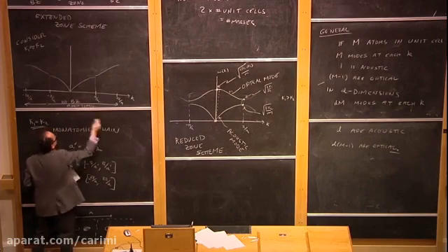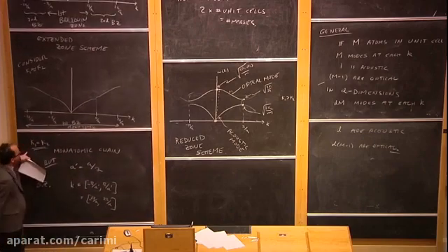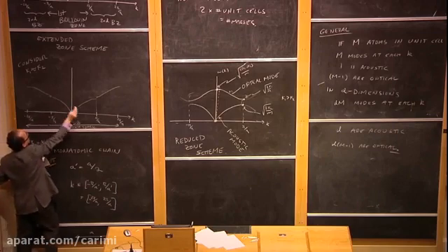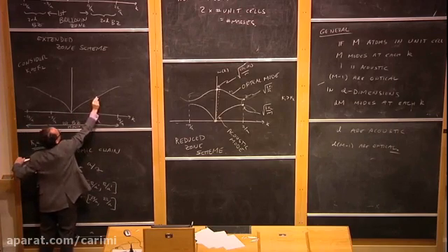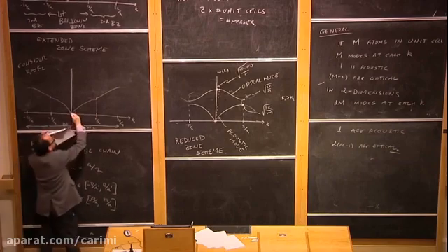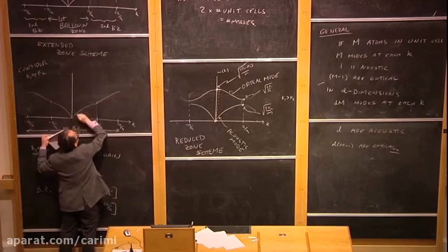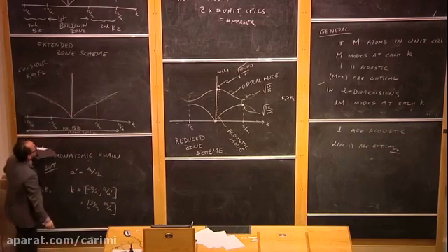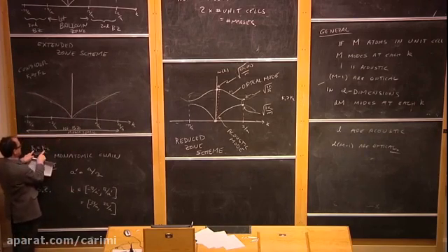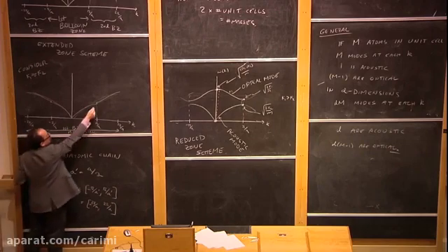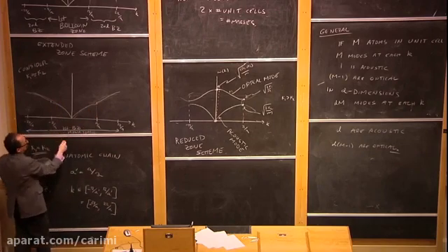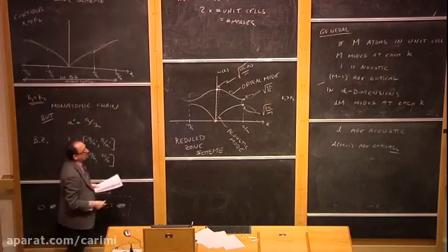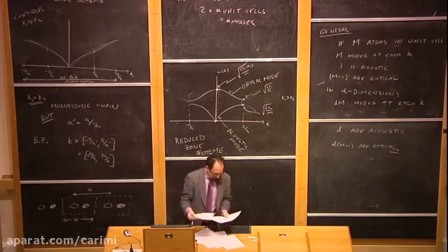Monatomic chain. And then if you make kappa 1 and kappa 2 slightly unequal, you open a small gap at the new Brillouin zone boundaries at pi over a. But really, what's underlying is a single mode for the monatomic chain from here to here and here to here, just a single connected mode, and when you make kappa 1 and kappa 2 slightly different, you open up a small gap at the Brillouin zone boundary, with the new smaller Brillouin zone associated with the new larger unit cell.